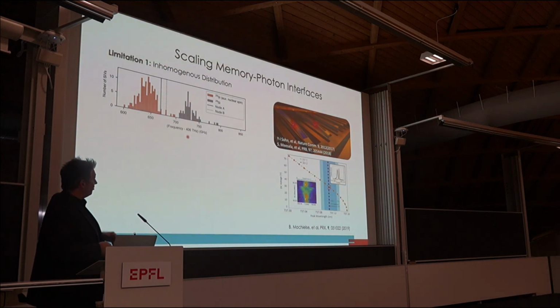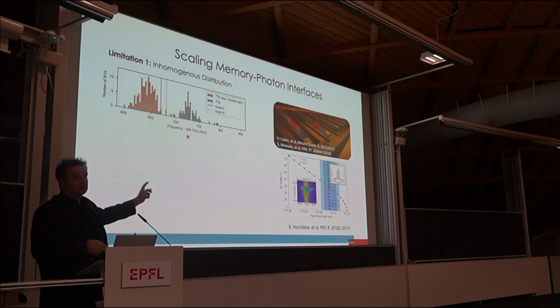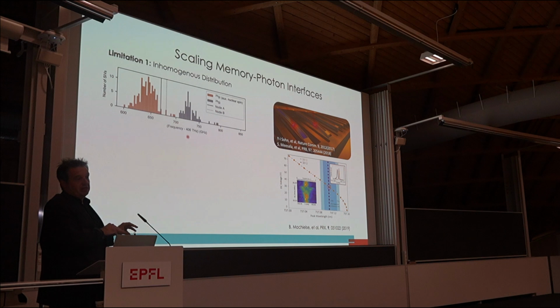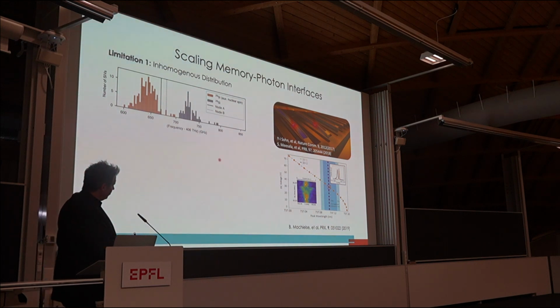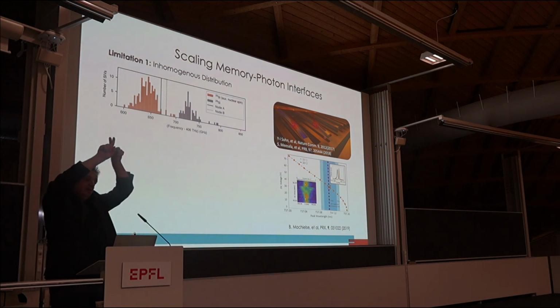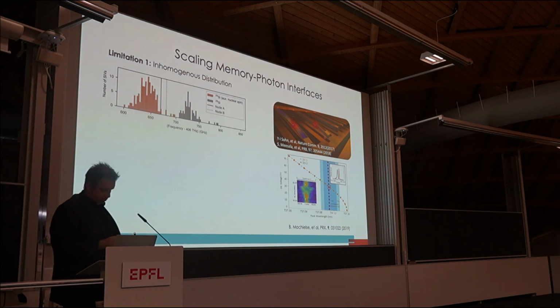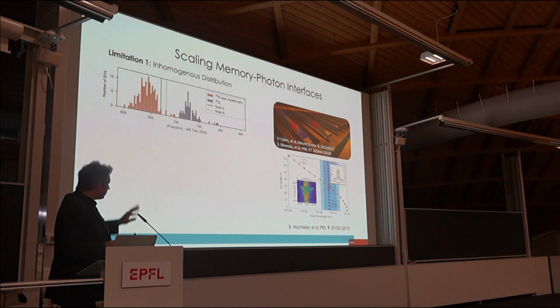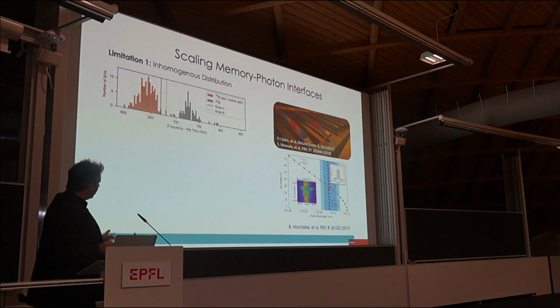One way that we've done over the years is using strain. The reason why they are broadened inhomogeneously is because there are strain variations in diamond. So the solution is to strain them even more so that the small strains actually don't matter anymore. So we pre-strain them using different approaches, and we were able, as this graph shows without me going into details, to take two silicon vacancy centers and apply strain using these cantilever structures. We were able to bring them together. And we can do this with many, many devices, I'm sure. But this is a little challenging, MEMS approach. We would like to do something a little different, as I'm going to show you.